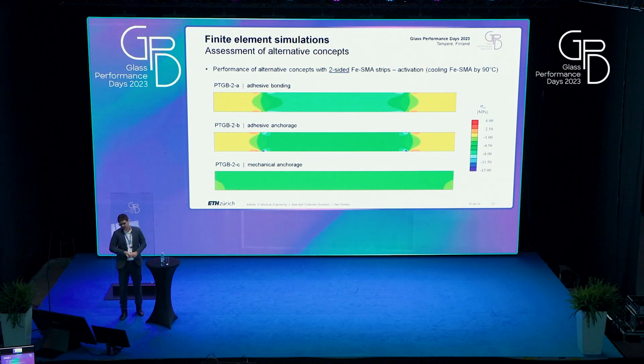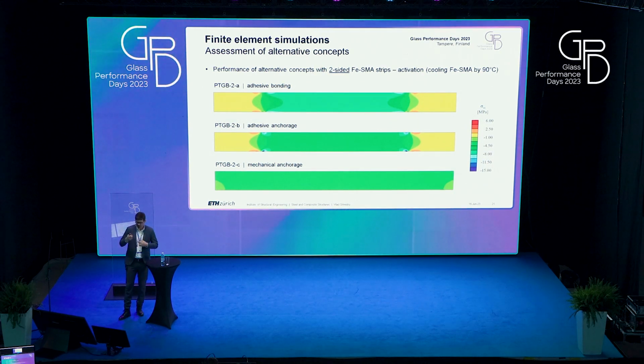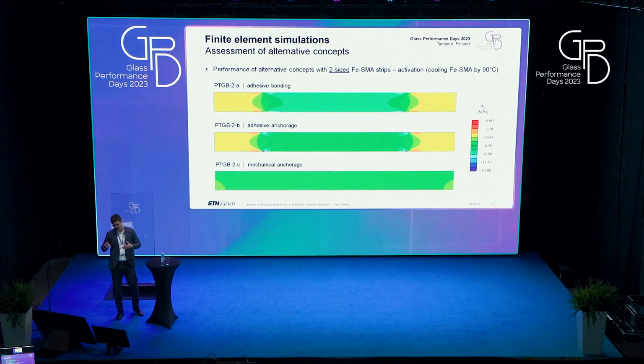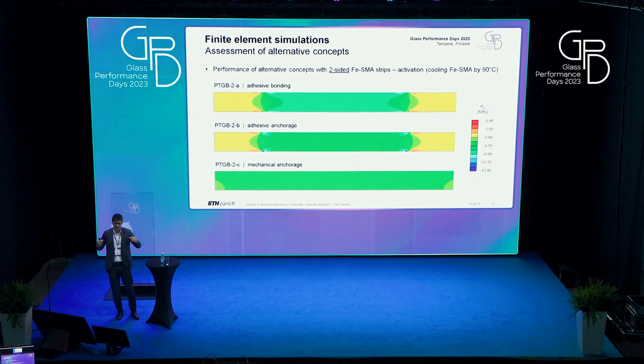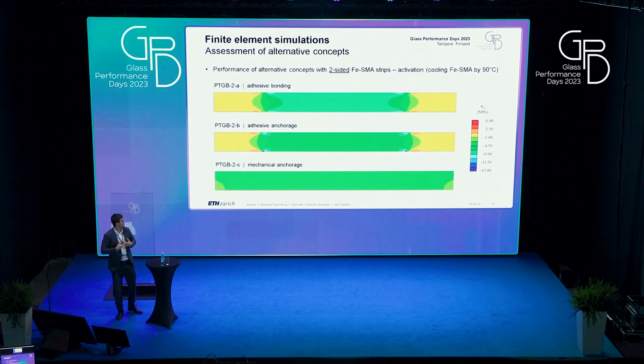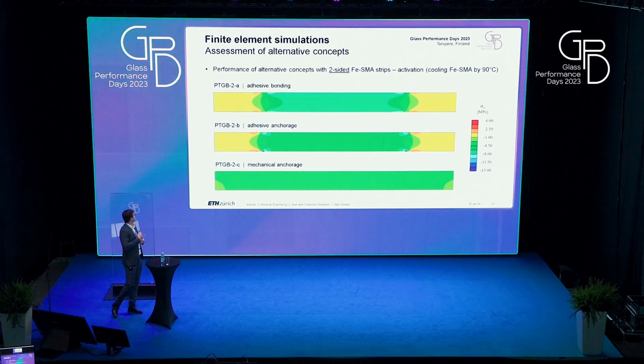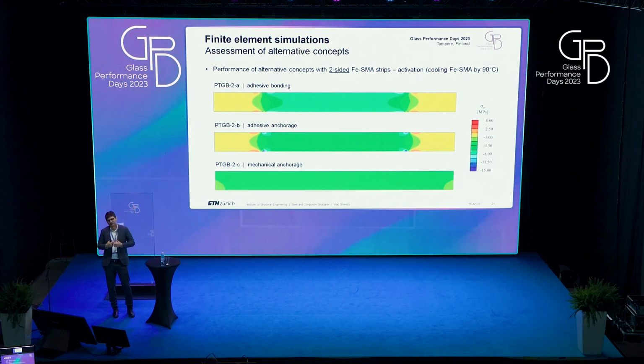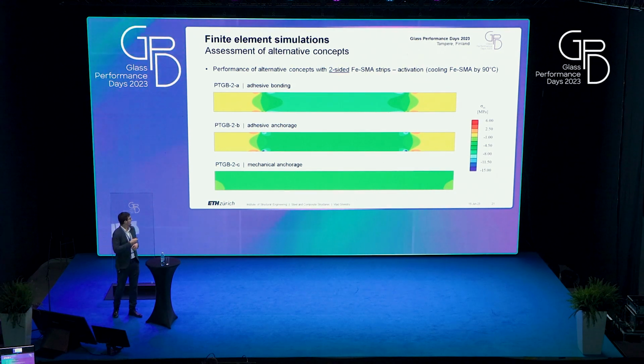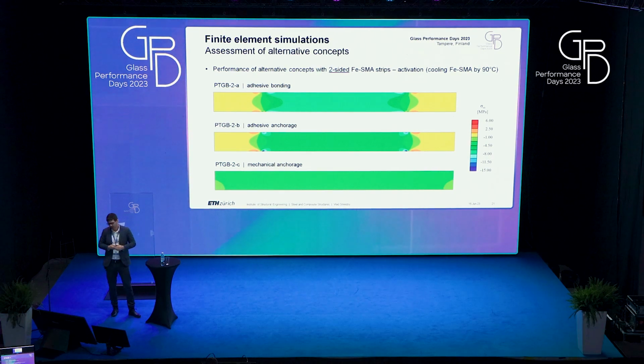So if we look now at the results for the concepts with two-sided shape memory alloy strips, in the activation for the beams with adhesive anchorage, we have the pre-stress only in the middle part, as you can see here. For the one with the mechanical anchorage, since we introduced the forces at the end of the beams, we have a pre-stress over the whole length of the beam.